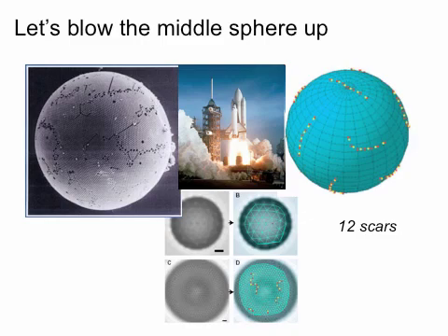Yeah? And what they did is basically, if it was 5 or 7, they had a colored dot. So if it was 5, it's a red dot, and if it's 7, it was a yellow dot. And they plotted that in 3D. And what they found was that in the ideal scenario, if the system relaxed to its lowest energy conformation, you had 12 grain boundary scars.